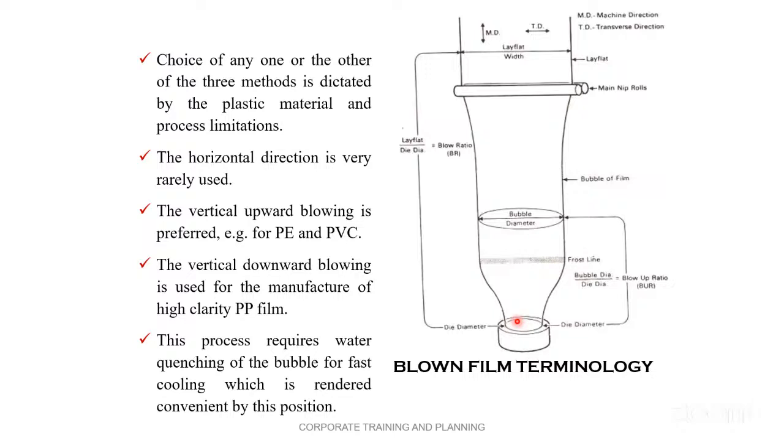But here you can see completely. This is completely transparent here, friend. Highly transparent, because here the polymer is in a completely melted form. But यहाँ से it will freeze. यहाँ से वो क्या बनता है? उसका film बनता है. Yeah, the actual film is going to be made here. But here is only melt. And therefore, this is called the freezing line. After this, it becomes opaque. This side, maybe some transparency, but here is a lot of transparency below the freezing line.